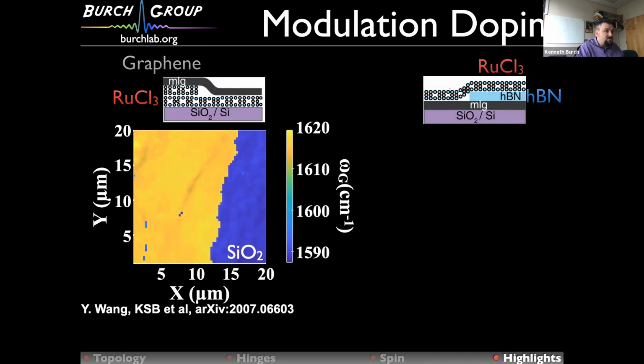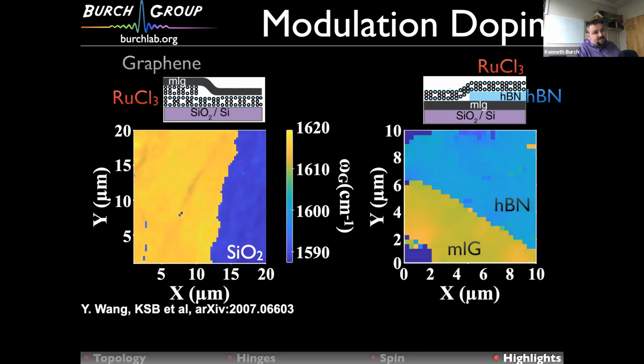We also checked this story with HBN. So indeed, if you put the HBN in the middle, you can still see charge transfer through the HBN. In this case, it was 5 layers, so it wasn't a huge amount of charge transfer, but nonetheless, it was there. And just again, to give you numbers, in this particular device, in the monolayer graphene touching ruthenium chloride directly, we see charge transfer on the order of 2 times 10 to the 13. And when we go over HBN, it goes down by a factor of 4, something like that.